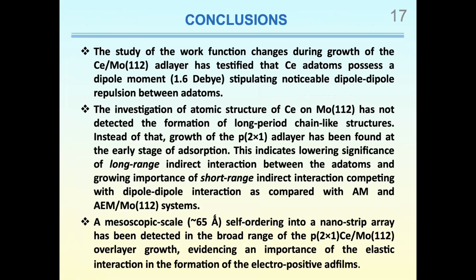As a conclusion, we can say that the study of the work function changes during growth of the cerium-molybdenum 112 layer has testified that cerium atoms possess a dipole moment of about 1.6 debye, stipulating noticeable dipole-dipole repulsion between atoms. The investigation of atomic structure of cerium on molybdenum-112 has not detected the formation of long-period chain-like structure. Instead, growth of the primitive 2x1 layer has been found at the earliest stage of adsorption. This indicates lowering significance of long-range indirect interaction between atoms and growing importance of short-range indirect interaction, competing with dipole-dipole interaction, as compared with alkali metals and alkali earth metals on molybdenum.